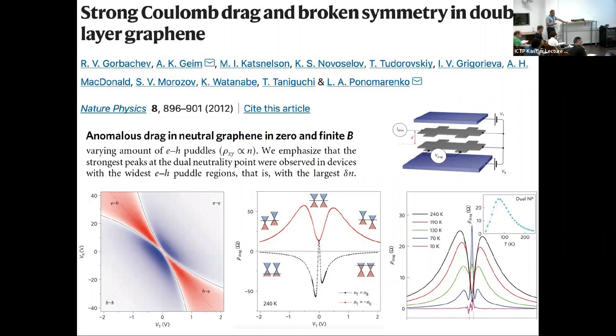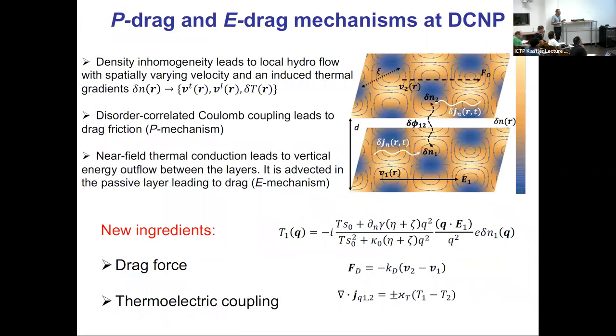Usually we think about drag as transferring momentum from one layer to the other layer, but at charge neutrality this mechanism doesn't work, because all of the transport goes through a relative mode and you cannot drive the hydrodynamic flow, it's impossible. So the momentum transfer mechanism is supposed to give zero drag resistance. Then Leonid Levitov came up with energy drag. So I'll try to give a quick sketch of a combined picture. The momentum drag actually survives, but it requires a bit more